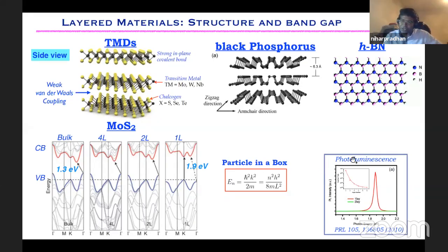And if we look at the photoluminescence, one of the quantities that you can measure, for the single atomic layer, this is the red line, which shows extremely high photoluminescence compared to just two atomic layers of the same material. So by using the single atomic layer of these materials, particularly transition metal dichalcogenides, you can use them for many different applications, particularly LEDs. That's what we are looking for, the high light emission.